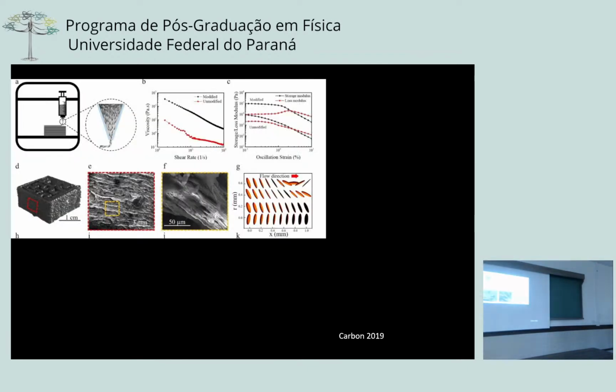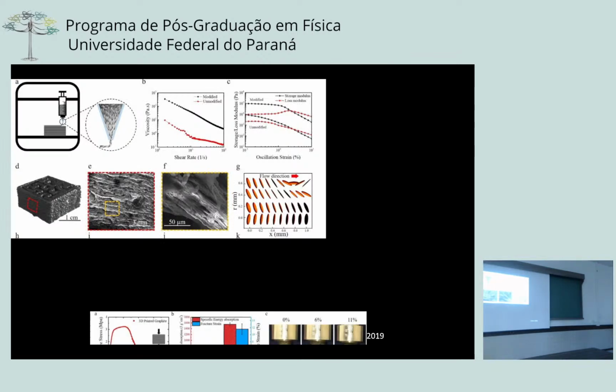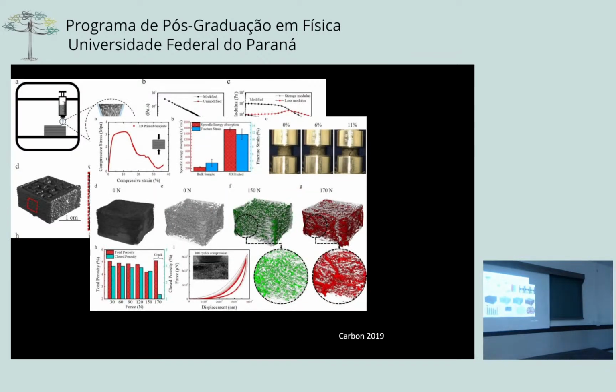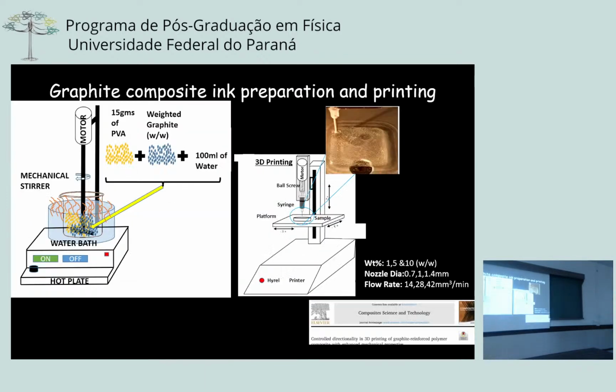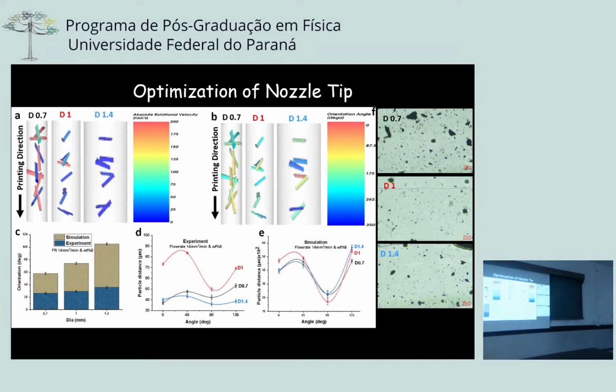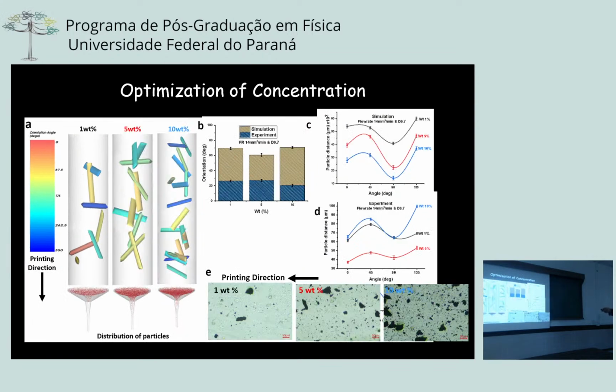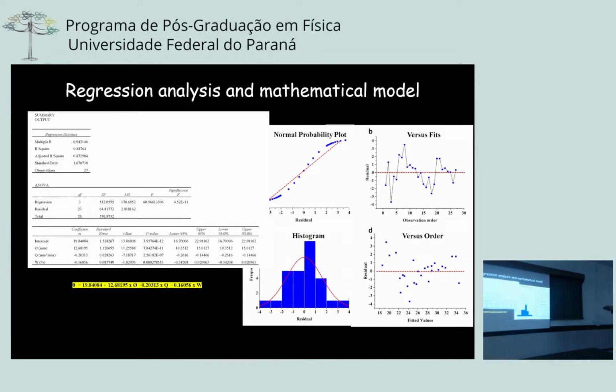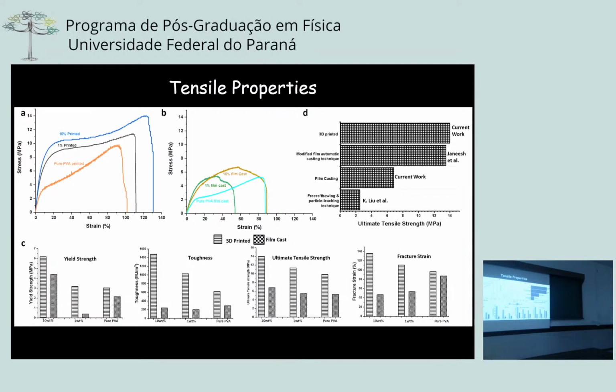We started looking at 3D printing of nanomaterial. We 3D print graphene, where we can have strength, we can tune ductility, we can have conducting 3D printed porous structure of graphene as well. We started looking at aligning the composite as well with 3D printing of direct ink. So what you do here is you take the matrix, put the graphite, make an ink out of it, and then print them. You can tune all sorts of processing conditions, establish a relation between processing condition and their mechanical property, where you can introduce anisotropy in your composite.